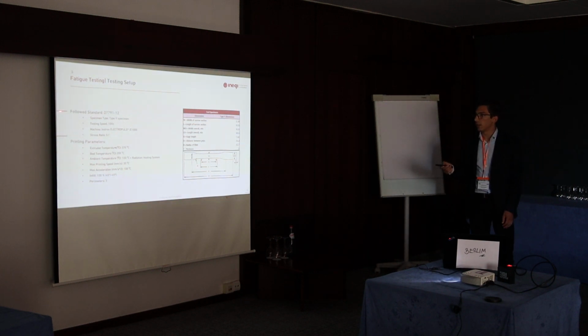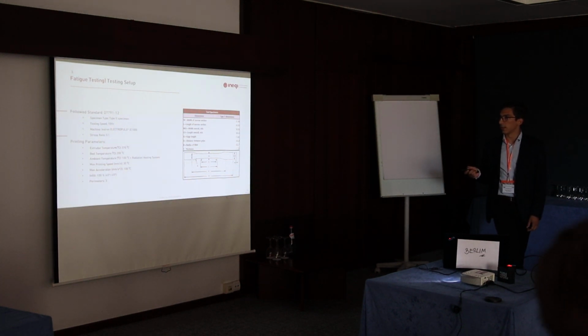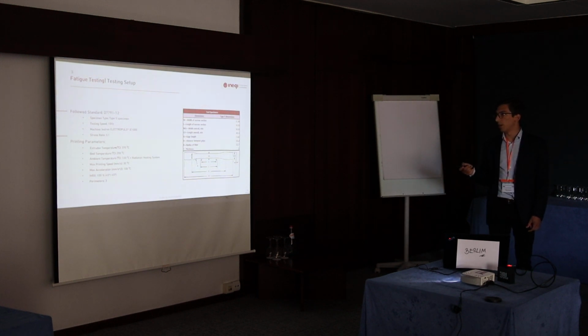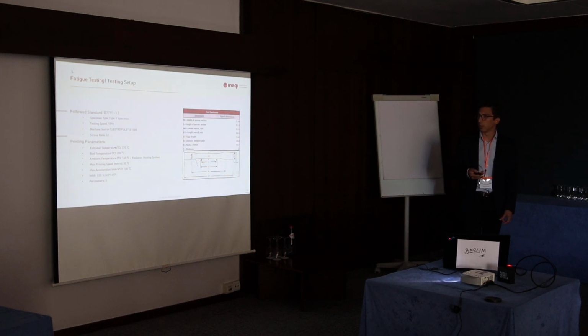In terms of fatigue testing, we use this standard in which you use the exact same specimens as the standard states. The frequency that you use for testing is 10 Hz. The only concern is the heating of the specimens, but from the first testing we control this using a thermographic camera, and we were able to tell that there was no particular heating that we believe would affect the performance of the test. We used the same machine, and in this case we did tests with a stress ratio of 0.1.